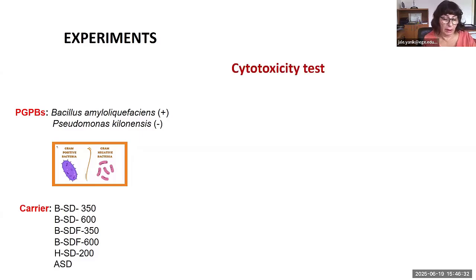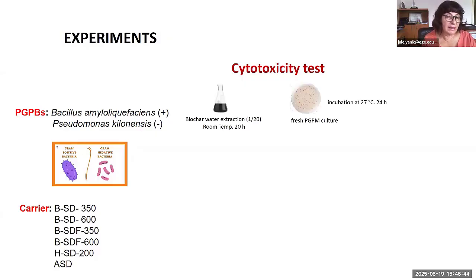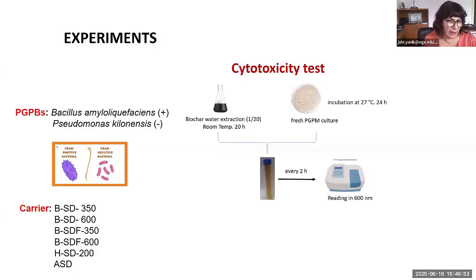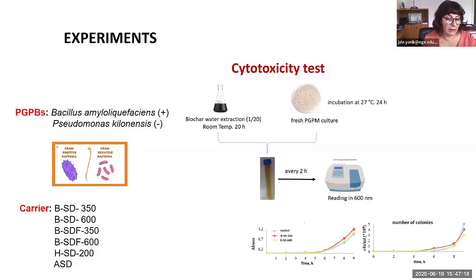Biotoxicity is critical when using biochar as a microorganism carrier. For this reason, first we performed a cytotoxicity test with our biochars and activated carbon. This is a very simple test. First, biochar was extracted with water, and the biochar water extract was added to the bacteria culture and incubated. Every 2 hours, 1 milliliter of solution was drawn, and the number of bacteria was determined by UV. If the curve is parallel to the control curve, it indicates that the biochar is not toxic.